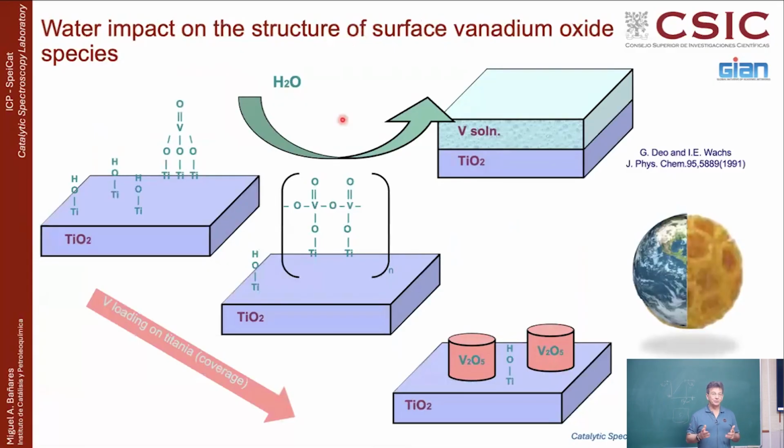How important is water? Very important. We already know that a supported oxide, as I've been showing you, is dispersed on a support, it can be like vanadium, and a support like titanium will have hydroxyls, and we already know that the vanadium will react with these hydroxyls, and then we will get titanium-oxygen-vanadium bonds until we run out of available hydroxyls.